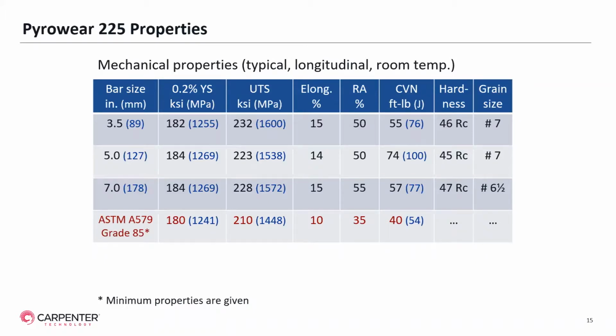But what we're most proud of is the third column from the right, the Charpy V-notch impact energy, where we're getting, even at these high strength levels, very good impact toughnesses ranging from the mid 50s to the mid 70s in foot-pounds. Hardness ranges typically between 45 and 47 Rockwell C, and we get good grain sizes. Even in the larger size bar of 7 inch, we're still getting 6.5 ASTM grain size number. Now this alloy is included in ASTM A579 as grade 85, as I've given those minimum properties in the bottom row.